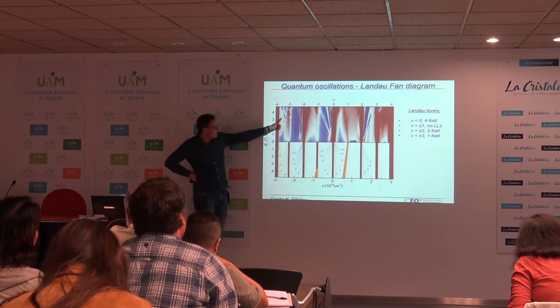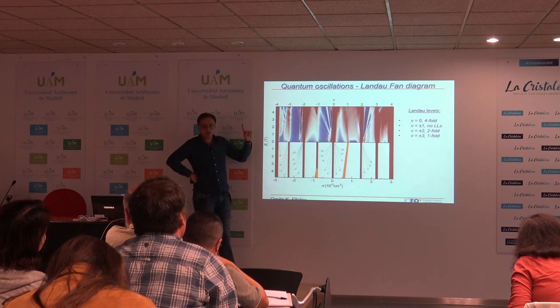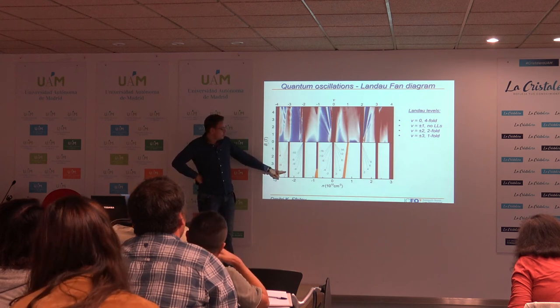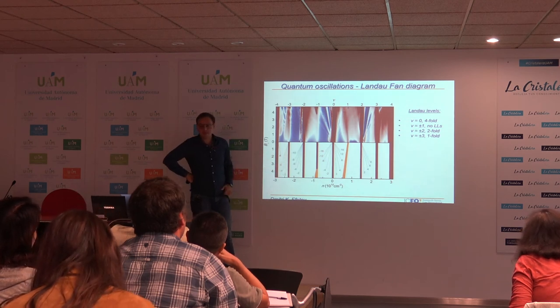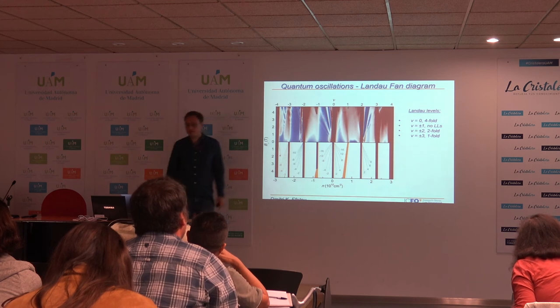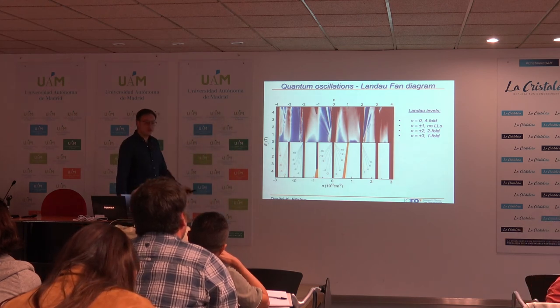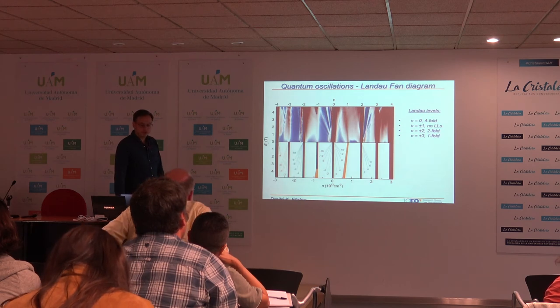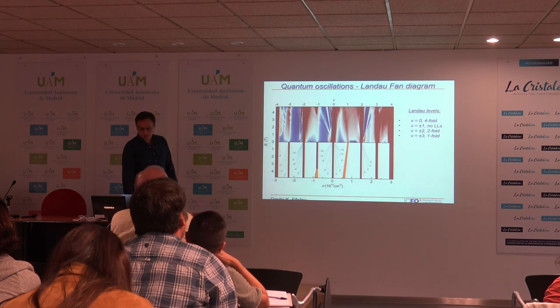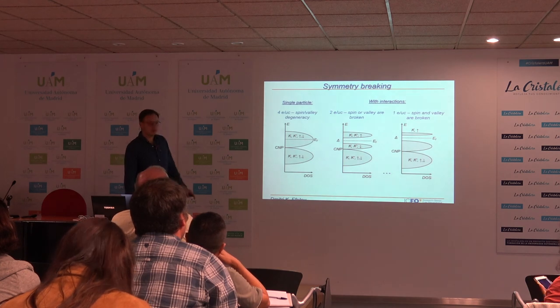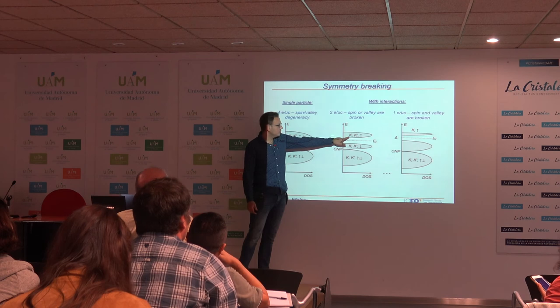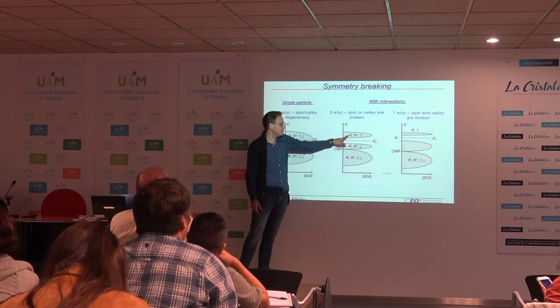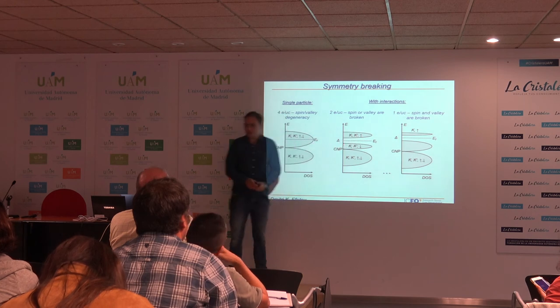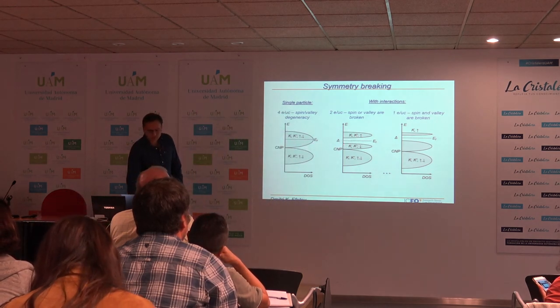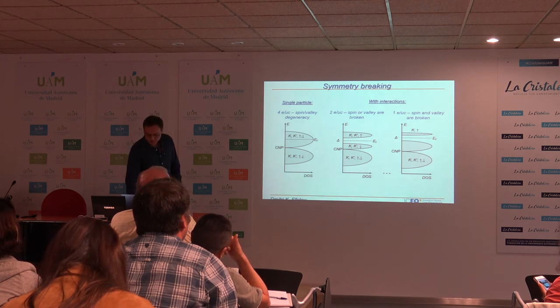And then if you go to the minus 3 state here, where presumably we have only one electron per unit cell, we have no degeneracy at all. So really the sequence is 1, 2, 3, 4, and so on. And so presumably some of these states have to be both K and spin broken. So this gives us some first clues of how to understand the underlying states. This brings me again to this picture. You can change spin, so maybe these are valley broken and these are spin broken, etc. We don't really understand conclusively yet what the underlying picture is.